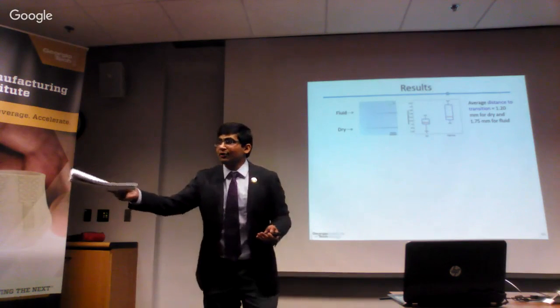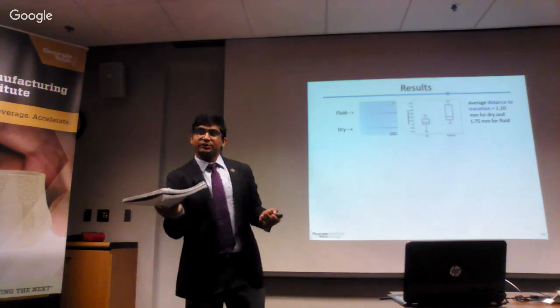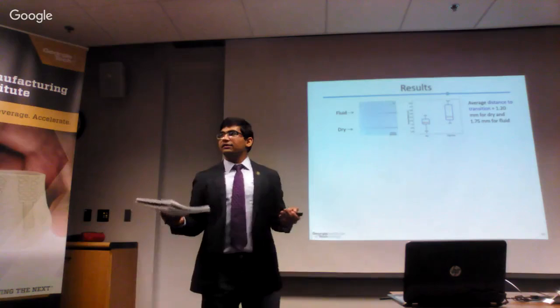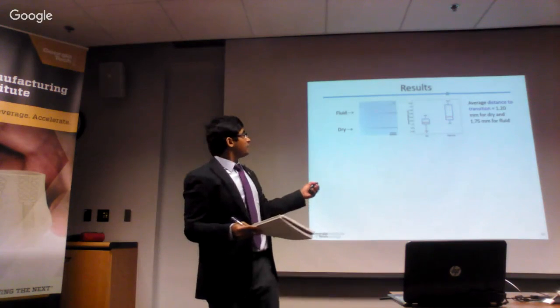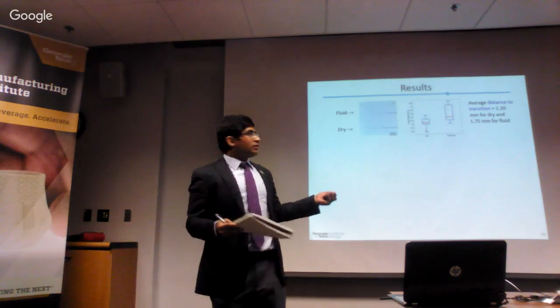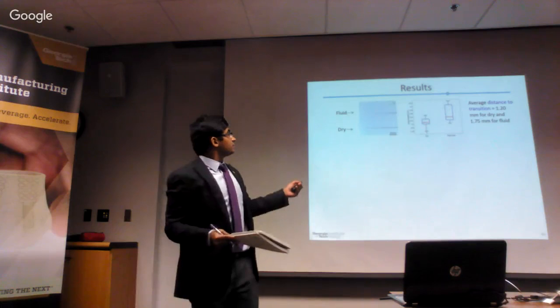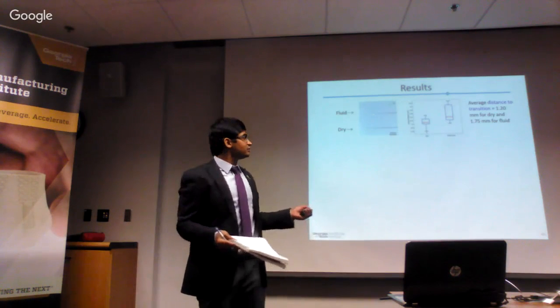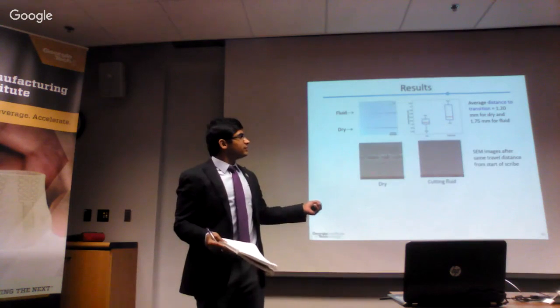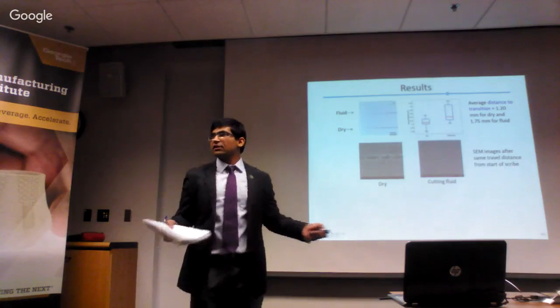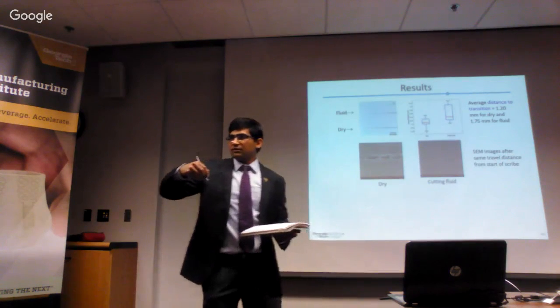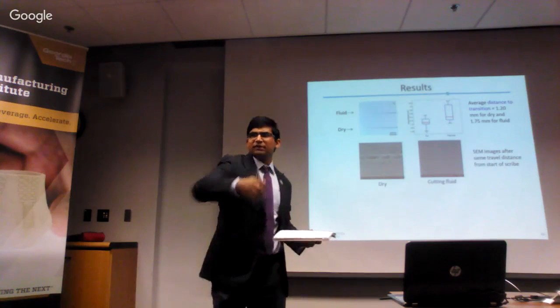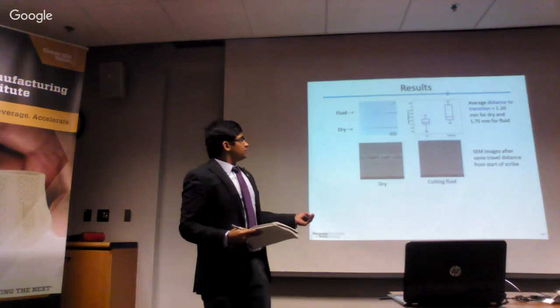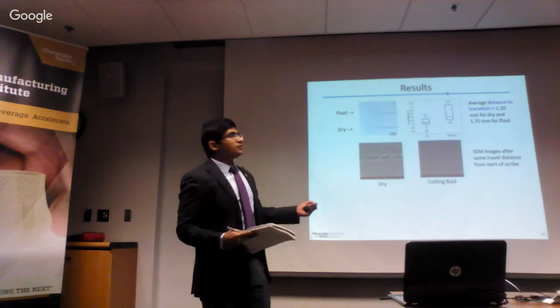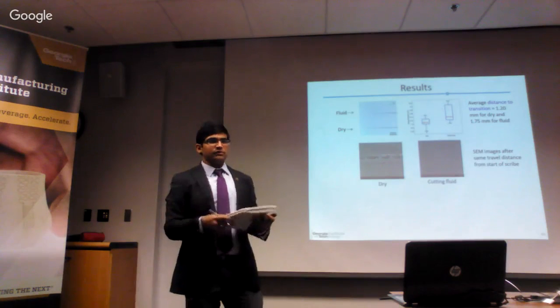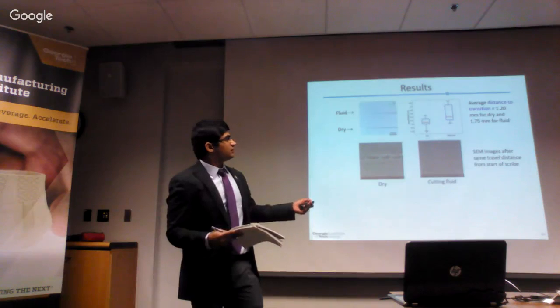But I'll build on what you just said. One of the possible ways in which we can address this question is if the depth of cut is the same or almost similar. Was it the same? That's the question. The depth of cut was measured at the critical depth of cut, which is the ductile to brittle transition. These are possibly at the same depths because they are at the same travel distance. So we are using the same increase of depth, 5 micron depth of increase over 5 millimeter. That's the scribe used. So they're expected to create the same depth because we are using the same machine condition. But in one case here, we see there's not much cracks formed.